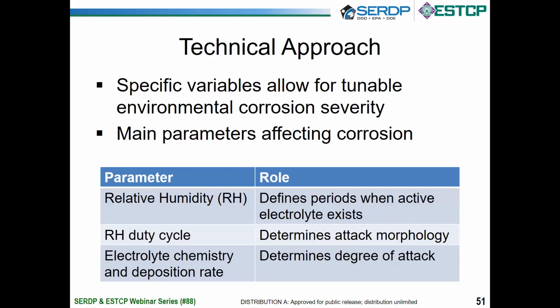So we've identified these three parameters to be the main parameters that we can tune to change either the attack morphology or the degree of attack. And so we're using this information, a lot of which was provided during WP 1673, to design and test our new accelerated corrosion test methods with this effort.